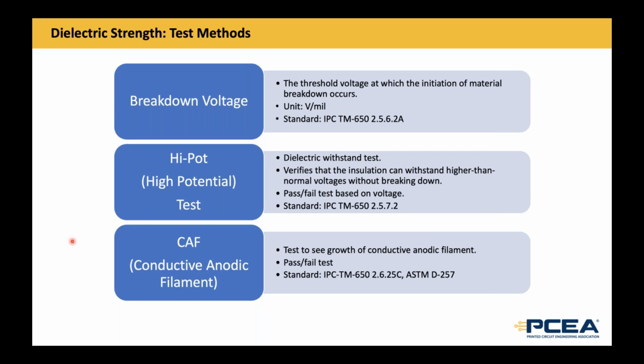Another way to look at dielectric strength is the CAF, the conductive anodic filament test. The material is monitored when voltage is applied to see if there's growth of conductive anodic filament. There's a lot more depth into each of these tests, but I won't have time to cover it. I would like to mention a few things to consider: choose material that meets the application voltage requirement, because if the laminate cannot handle the expected voltage and breaks down prematurely, the device can malfunction. For higher voltage designs, such as telecom applications that consume a lot of power, consider materials that have higher dielectric strength.